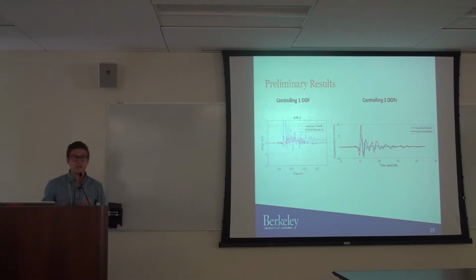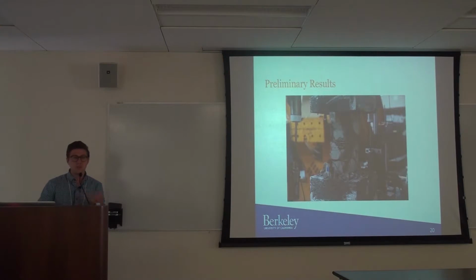But we're still having some issues with the OpenFresco element. Originally, we were using the 3 actuator element, but it has some issues because it was designed for a 2D model, but our actual model is 3D since we're going in the transverse direction. So trying to update that to work with a 3D model has taken some time. And so until we do that, we didn't want to move on to our corroded specimens. So those are sitting in the lab waiting to be tested. Well, now I think the 3D model is finished, so now we're just waiting for some other tests in the lab to finish up. But we're on the cusp of getting that.